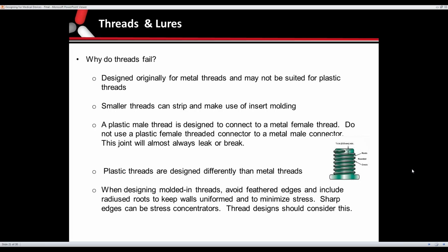They're definitely better than a metal thread. You want to avoid edges on these because that'll affect the fit. You want to make sure that the 2 mating materials are compatible as far as shrink rates, as far as the rigidity and so forth of the 2 materials. That way the fit is what you desire. Yeah, and add radiuses at the roots of the threads, keeping walls uniform, minimizing the stress. Just like we talked about earlier, sharp edges can introduce stress into the parts. Good lead in to the threaded area as well.